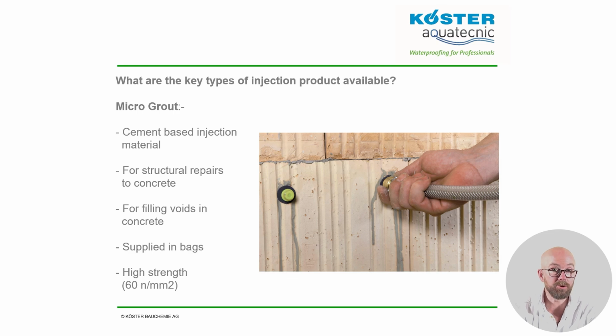Where microgrouts really come into their own is for filling large voids within concrete. With microgrouts, we can fill voids with a product of a similar strength and characteristics of the concrete surrounding it. The material is supplied in powder form and is simply mixed with water. It's pumped using a peristaltic pump or any other grouting pump. The final compressive strength after 28 days is 60 newtons per millimetre squared.